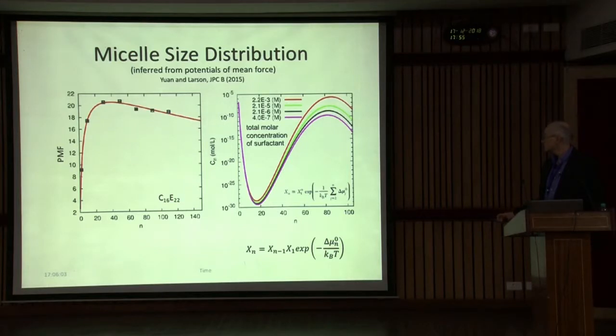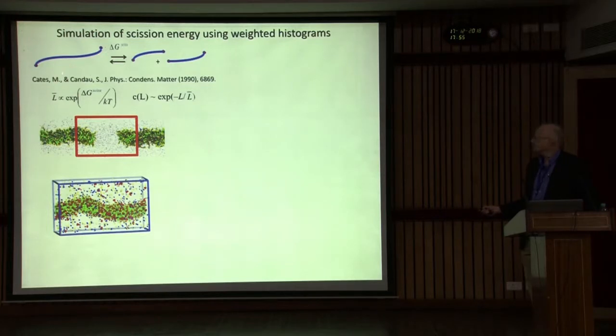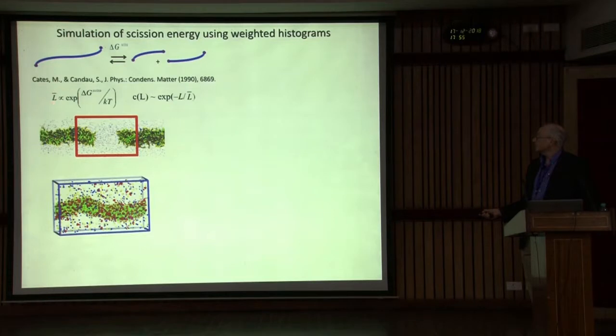This is significant because getting this by direct simulations would be practically impossible, but we can extract it using potential of mean force. This particular surfactant has a C16 tail and a big ethoxylate group, so we didn't know ahead of time what the typical micelle size was. If you have a salt added or a different surfactant, you can get growth of long thread-like micelles. The length of these micelles is related to what's called the free energy of scission — the free energy cost of breaking a long micelle into two shorter ones. The average length and entire distribution of micelle lengths are related by the Boltzmann principle to this scission free energy.